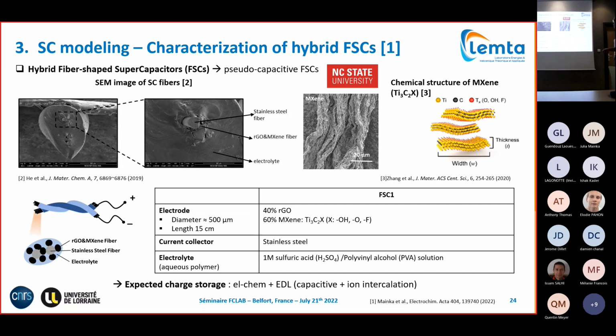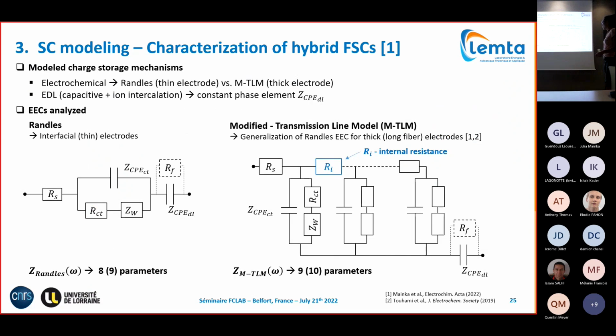So when we model it, we include it in the EDL, actually as charge storage, just like classical capacitive charge storage. So this is our active material. The electrolyte was a classical aqueous electrolyte, sulfuric acid, and they used as well some stainless steel current collectors. So in these devices, one electrode is composed of two current collectors, which assemble four used graphene and MXene fibers, and they twist it together to form these fiber supercapacitors.